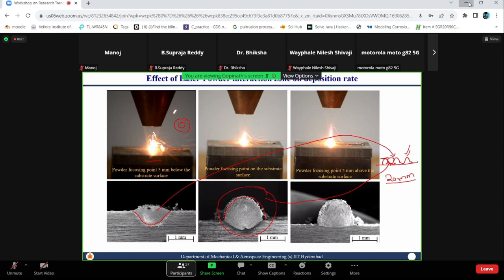Because the moment you have a cutting tool, which is a physical tool, and it has to go and remove the material physically, then you will need a very complex kinematic system. And you are actually removing the material, producing chips, which essentially wastes the metal powder. So it's not sustainable. This is where you can do one more magic. You just switch off the powder flow and allow the laser to come out of the nozzle and quickly scan at a higher scan speed in such a way that these partially fused particles get melted, only a thin layer, 100 micrometer, that's it.